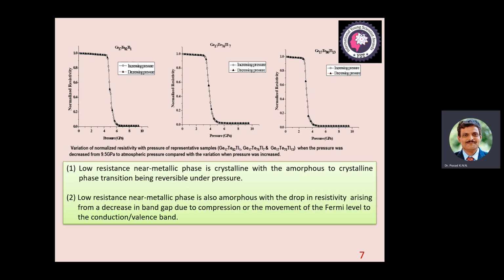The low resistance near-metallic phase is also amorphous, with the drop in resistivity arising from a decrease in band gap due to the compression or the movement of the Fermi level to the conduction or valence band. So the moment we apply a very high pressure on our sample, which is very small in size, being a semiconductor, we could notice a decrease in the energy band gap due to the compression or the movement of the Fermi level to the conduction band or the valence band. This is another observation that we made before and after pressurization.